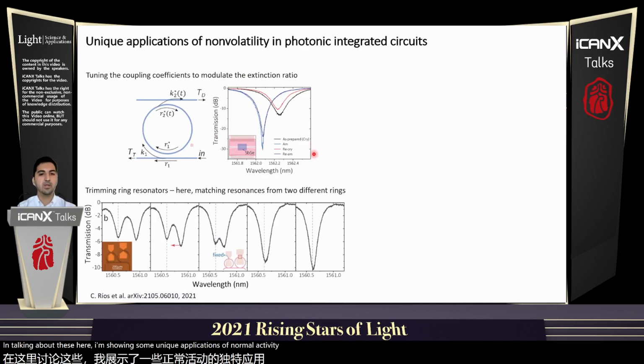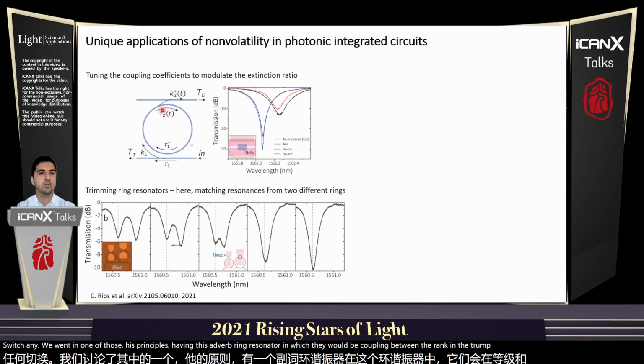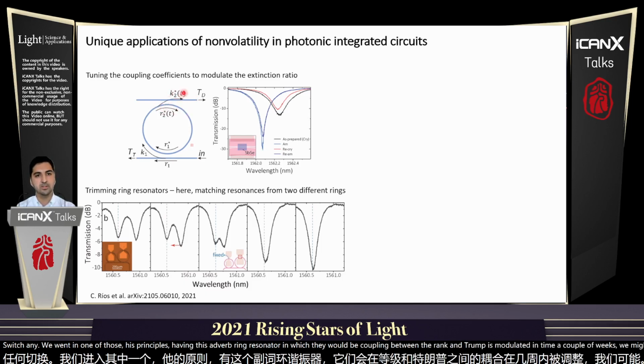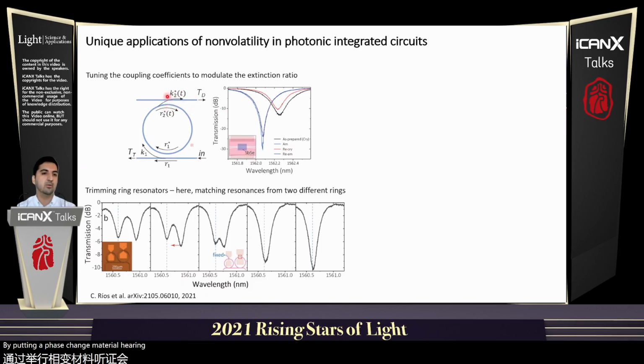There are some applications where we don't even need reversible switching. One of those is, for instance, an add-drop ring resonator in which the coupling between the ring and the drop port is modulated in time. We modulate and tune these coupling coefficients by putting a phase change material here in the middle, as shown in this picture.